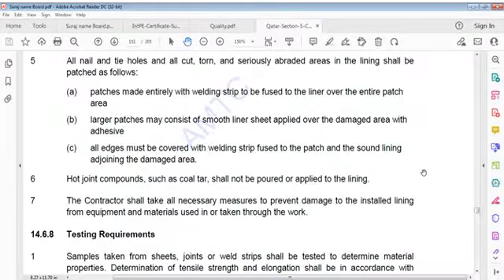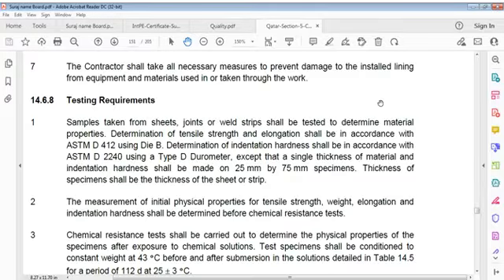All nail and tie holes, all cut, torn, and seriously abraded areas in lining shall be patched as follows. Patches made entirely with welding strip to be fused to liner over entire patch area. Larger patches may consist of smooth liner sheet applied over damaged area with adhesive. All edges must be covered with welding strip fused to patch and sound lining adjoining damaged area. Hot joint compounds such as coal tar shall not be poured or applied to lining, from equipment and materials taken through work. Testing requirement.